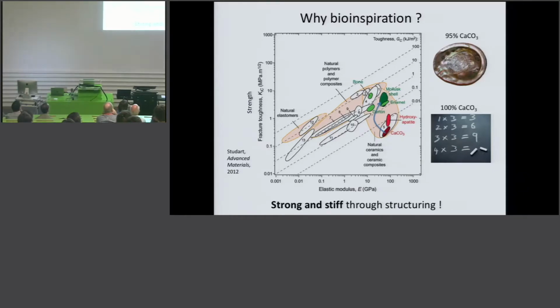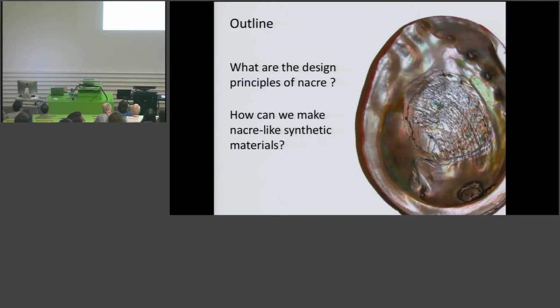And what I would like to highlight here is that the seashell itself has 95% of calcium carbonate, which should be down here in the diagram. So it's a fairly poor material in terms of mechanical properties. But through structuring, the organism is able to increase the toughness of these materials by orders of magnitude, even if it's made out of 95% of calcium carbonate. So how does it do that?